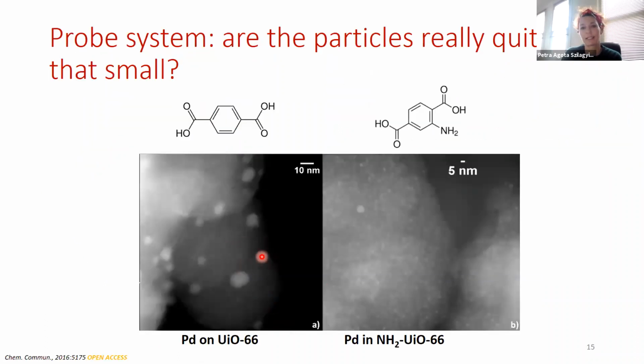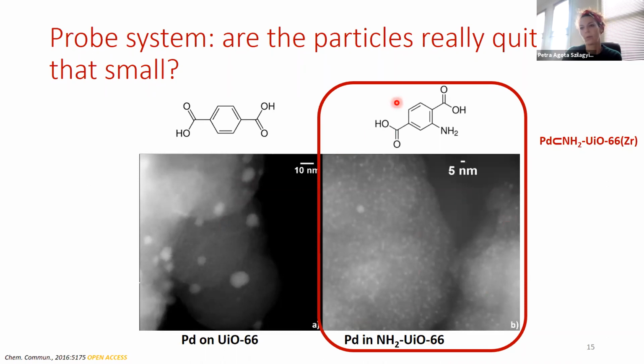Furthermore, we had previously shown that when the linker has an amino group on it, while the crystal structure is identical, in the pristine framework we don't embed the palladium particles in the pore. So you can see that larger nanoparticles are supported on the external surface of the framework. At the same time, when we have a functional group, the palladium particles are very small, below 1 nanometer, and very well dispersed. So we decided to go with this particular composite.